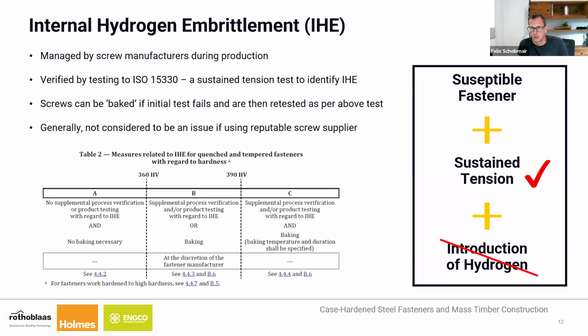It's something that the good manufacturers are doing by rights now. And if you had an IHE failure on site, it would manifest very, very quickly. So essentially during the install rather than afterwards, as with EHE, when you have external effects that have come into play. Yeah, and essentially what you're doing through these tests is you're showing that there hasn't been any hydrogen introduced into the screw during the manufacturing process.